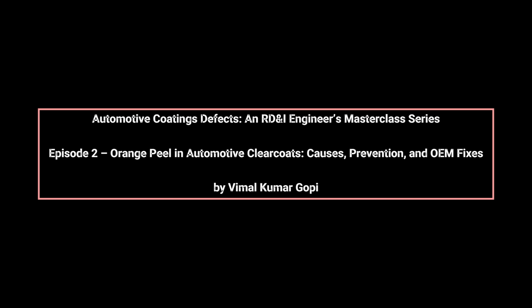The result is a wavy, dimpled surface that resembles the skin of an orange, where reflections appear distorted under directional lighting or reflection tunnels. Correctly identifying this defect is essential, as misdiagnosing it as a spray problem alone often leads to unnecessary equipment adjustments, wasted material, and repeated rework.